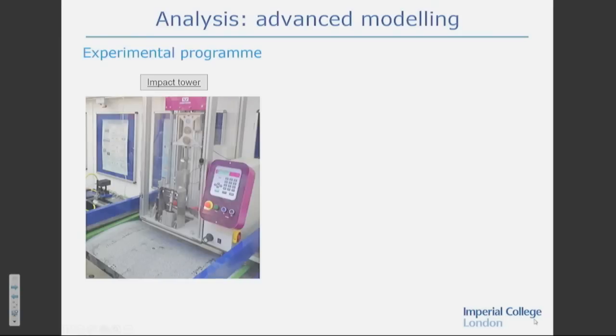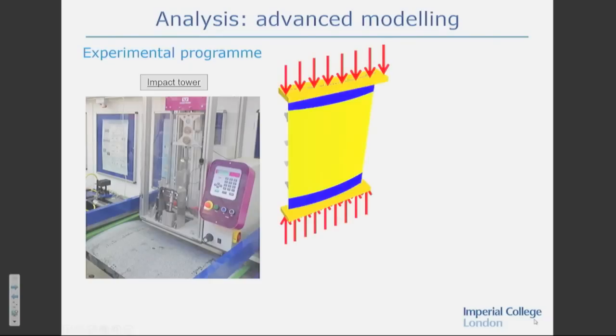Here's the impact tower we were doing the impacts with in our lab. They were tested using a 250-ton compression machine that was designed and built by the Aeronautics department quite a few years ago, designed by a colleague, Peter Gasson. I think he's here tonight as well. And so doing this compression. And here's a high-speed camera image just to show the failure that develops. They were impacted here, and you can see the failure initiates from this zone and zips across the panel like this. So that's what happened experimentally.